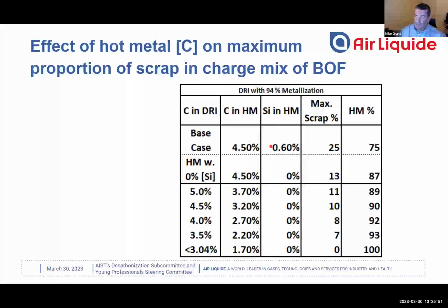Now, when we melt DRI in a submerged arc furnace, we're going to see very little silicon, experts tell me. And so this silicon is chemical energy from the oxidation reduction. And just from this loss of silicon, it's going to limit how much scrap we can use. And in fact, we'll have to go from 25% scrap down to 13% scrap. And this problem gets worse as the carbon content in the hot metal decreases. So 4.5% carbon in the DRI gives us only 3.2% carbon in the hot metal. Without silicon, this brings our scrap